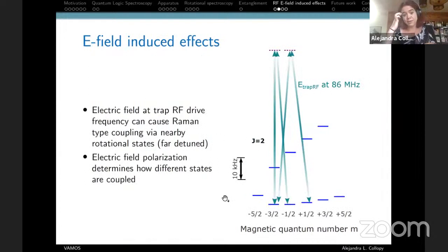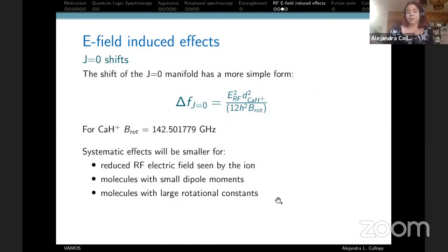And what we find is this RF electric field at the trap drive frequency can cause Raman type coupling via nearby rotational states. And when I say nearby, I still mean very far away. So our RF photons are at 86 megahertz. Our different rotational levels are at hundreds of gigahertz or terahertz away, and states within a manifold are at 10 kilohertz spacing or so. But we can see that these RF photons do mix states and can cause shifts. And the electric field polarization determines how different states are coupled. So if you have mostly sigma polarization, you can couple delta M equals 2. And if you have sigma and pi, you can couple delta M equals 1. We also see that this causes shifts between rotational manifolds.